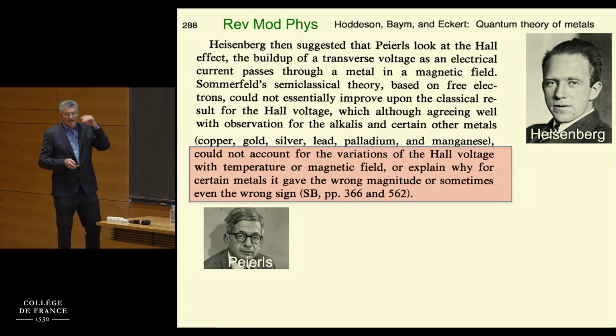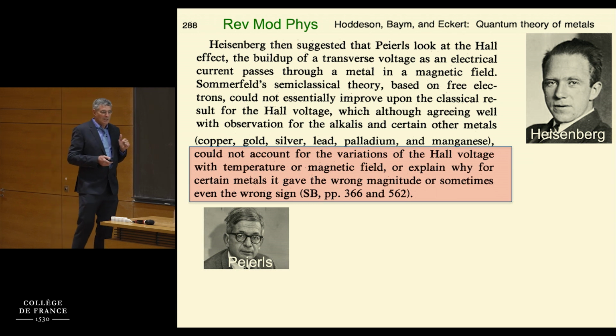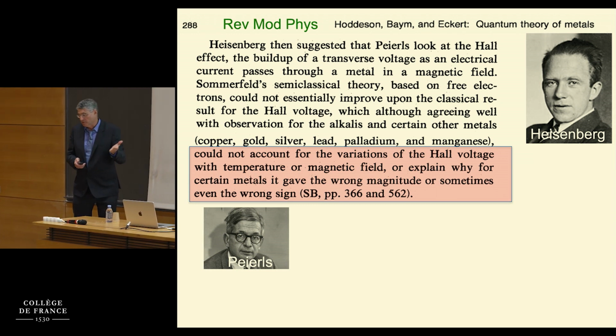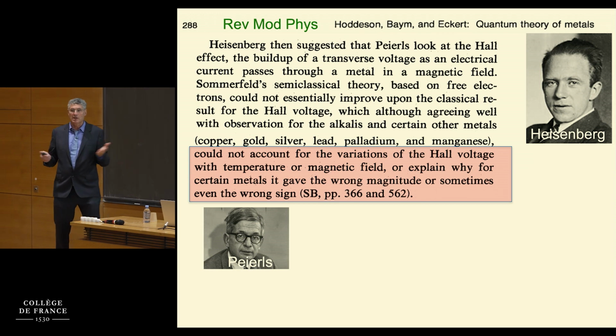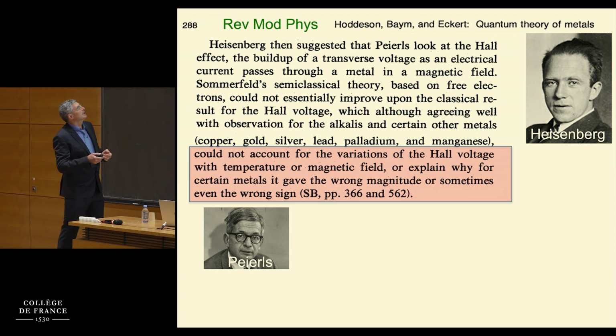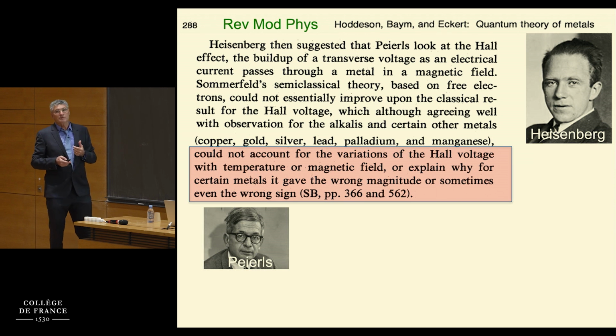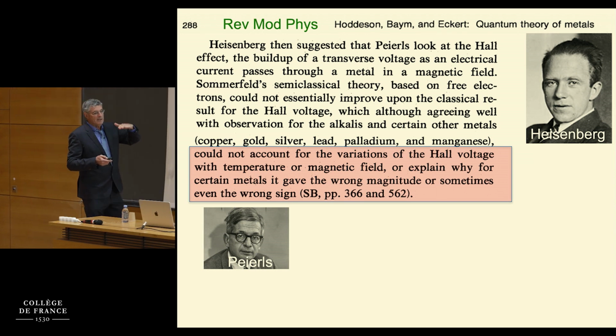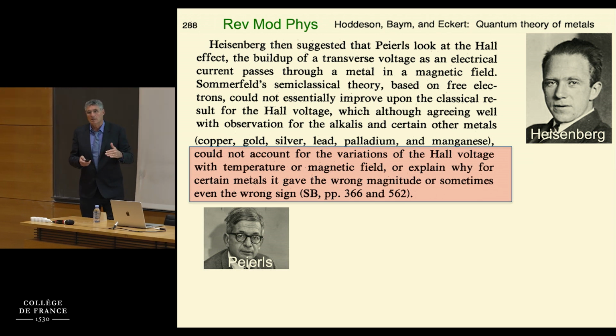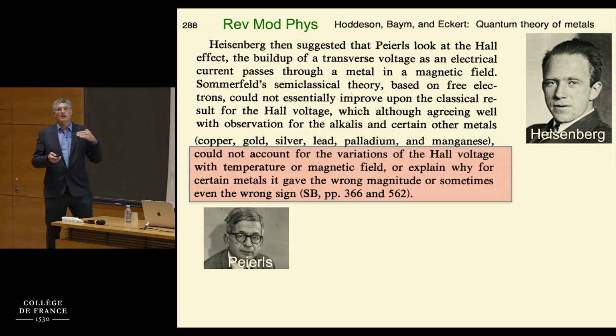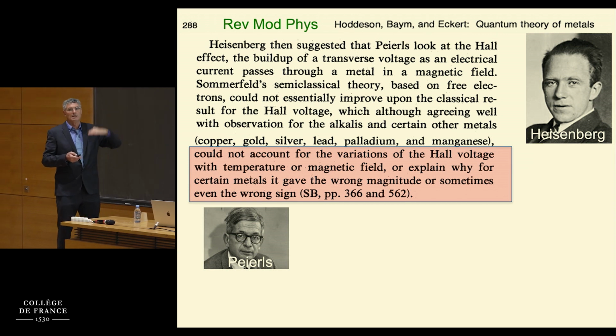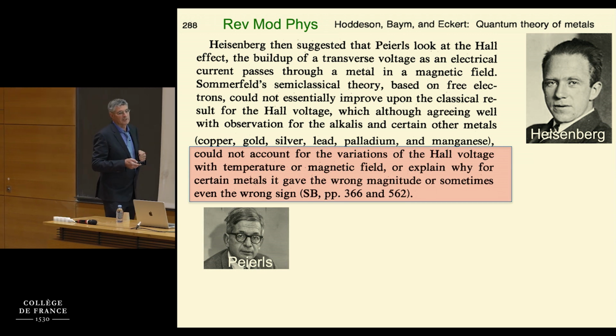Okay, so go back to history. Heisenberg gave Peierls a problem to look at the Hall coefficients of metals. Why? Because, as I said before, the Hall coefficient of metals should always be negative if you have electrons carrying the current. But apparently there were materials like gold, silver, lead, palladium, and so on that had positive Hall coefficients. And he asked him why. And Peierls worked on it, and of course he figured out that when you fill up a band and come close to the edge, effectively you should think of the carriers as holes, which are the parts that are missing to fill the band, and those holes will have a positive Hall effect sign.